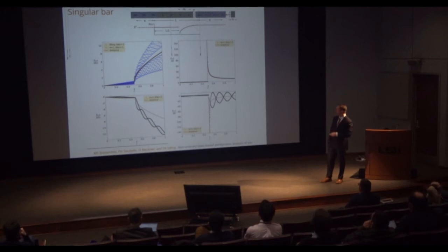And so, we were able to identify it theoretically, but also in a simple experiment. If you have a single bar, for which we had an analytic solution, in tension, the analytic solution is a red line that's right underneath the black line there. The black line is our simulations. The blue line is the original correspondence theory with no stabilization. So the original correspondence theory is unstable in this scenario, and under tension, our model works perfectly. This is a different measure, but also in tension, perfectly.